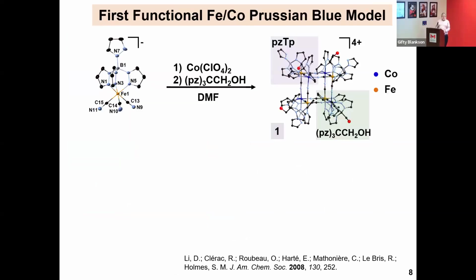All right, in terms of our first model complexes, we decided to start off simple and make molecular boxes. So we used tridentate capping ligands. With the iron, in this case the tetrapyrazolylborate, 3 of the pyrazoles are coordinating in a cis fashion to each other, that is 90 degrees between the nitrogen atoms and the iron, to give this tricyanoferrate 3 anion. In the presence of cobalt-2 perchlorate, and then subsequent addition of another tridentate ligand, trispyrazolyl ethanol, you can make these molecular boxes, tetracationic overall, and because of games we played with the ligand choice, we could get an X-ray structure.